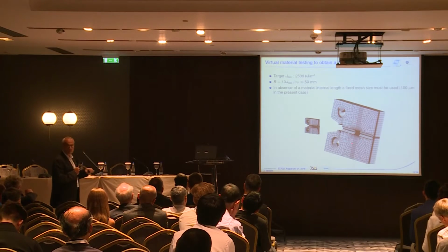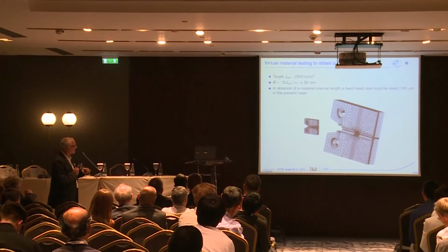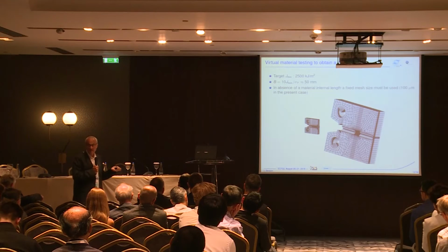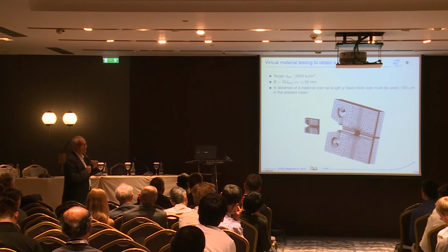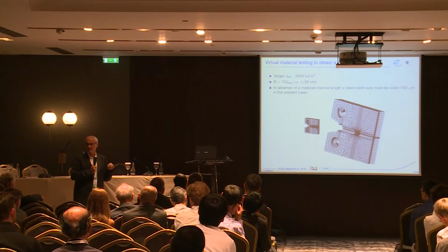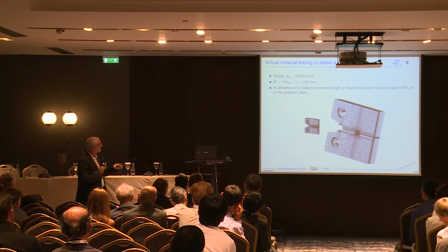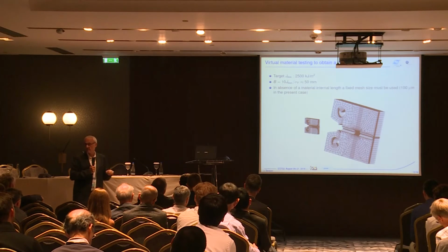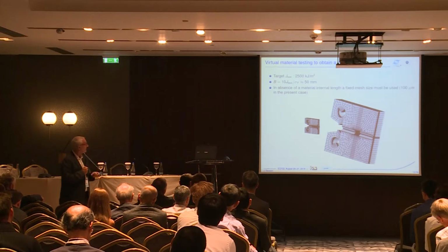You don't get this mesh just by applying some kind of homothety to get here from here, because we are dealing with damage, crack propagation, and if you're dealing with damage, crack propagation, there is an internal length. Here we're not using a non-local damage model, which I'm working on.